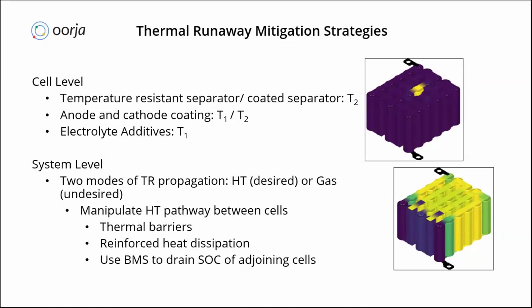Or you can also have the BMS drain the SOCs of the adjoining cells. For example, in the previous slide we were seeing that if the cells are at higher SOCs, the chances of those cells going to thermal runaway will be higher because of the thermal runaway signature at the higher SOCs. So whenever the BMS detects that one cell is going to thermal runaway, it can ensure that it is draining the SOC of the neighboring cells, so that you are reducing the risk of those cells getting into thermal runaway.